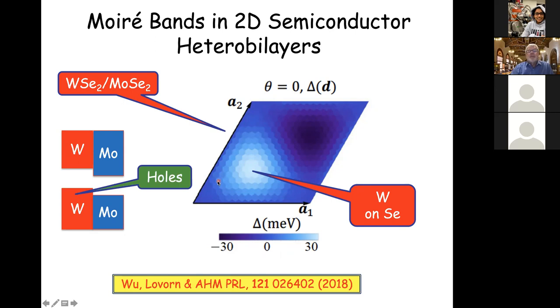And there are two actual effects that cause the energy of the states at the top of the valence band to vary as you move the molybdenum layer underneath. One is that there's a level repulsion effect that pushes the states in the tungsten up more strongly when the coordination is such that they are more strongly hybridized with the molybdenum orbitals. And the other is a simple electrostatic effect. If the metal sits on a negative ion on the other site, then it will see a repulsive Coulomb potential. And that creates this spatial pattern. Turns out that in TMD materials, the size of this modulation is some tens of milli-electron volts. There are now better estimates of this modulation strength in the literature.